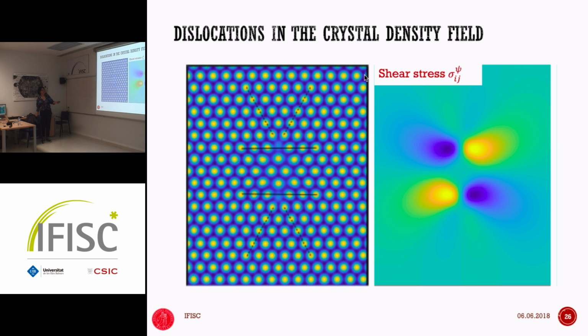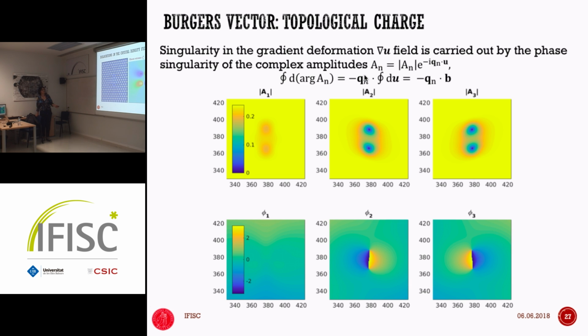You can also consider the case of two dislocations in two glide planes, and you can have this quadrupole shear stress. And the relation to the topological defects is that in the one-mode approximation, when we write the order parameter, we expand it in terms of these three amplitudes. If you look at the magnitude, it's a complex magnitude when you have a defect. One of those three is continuous, and there's no discontinuity next to the dislocation. But for the other two, in this particular case where we have two dipoles in two parallel glide planes, we see that there are two waves that have a topological defect in them. You can see very nicely the phase singularity, and the magnitude goes to 0 while the phase becomes singular. So they are topological defects.